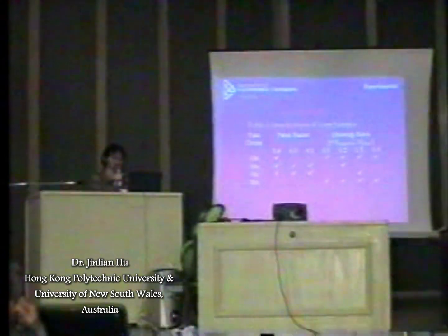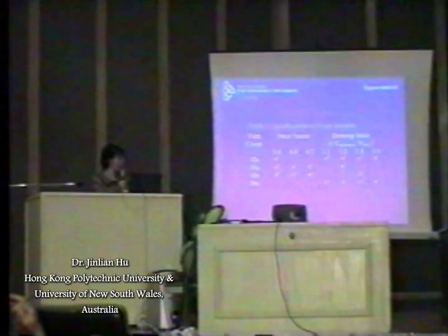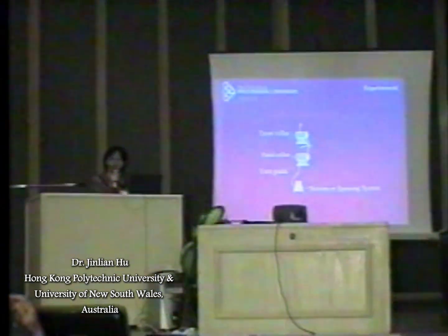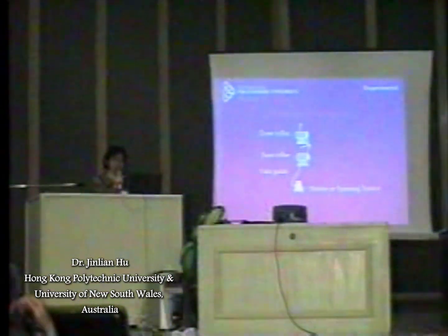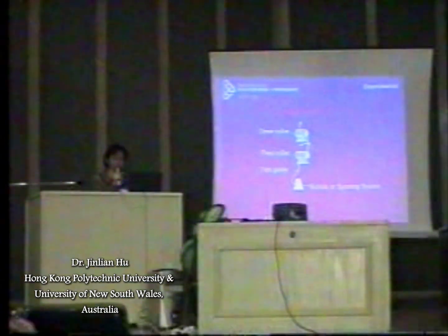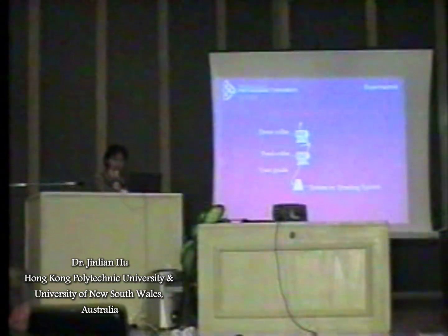We have different yarn counts, different twist factors, and we apply different drawing ratios, as shown in this table. Here is the tensile drawing device. We have a bobbin from the spinning system, and we have a feeder roller, and then a drawing roller. There is a speed difference between the drawing roller and the feeding roller. So the yarn is stretched, so it is tensile drawn.